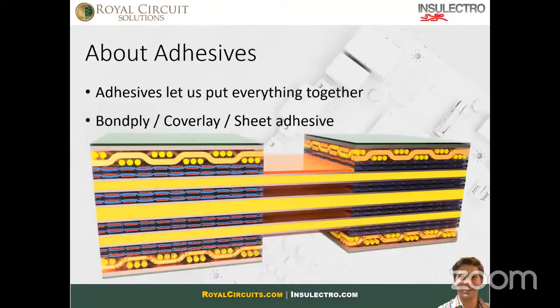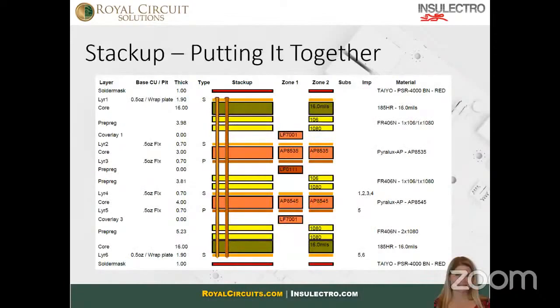So if you're trying to bend something and you have to have multiple transition lines going back and forth between different rigid sections, we want to do what's called a loose leaf construction, which is what you see here on the slide. When we want to, let's just say, only send one transmission line from one to the next, and we do need to bond together 3 different layers, right? Microstrip construction, where we have ground, signal, ground, we can do something like this in the stack up, where you can see we'll etch off one side of the AP core, and then we'll glue it together with another AP core using a bond ply instead of a prepreg, right? And that gives us the ability to, one, maintain constant distance between our ground layers and our signals, but also, 2, we don't need to bend multiple layers at once.